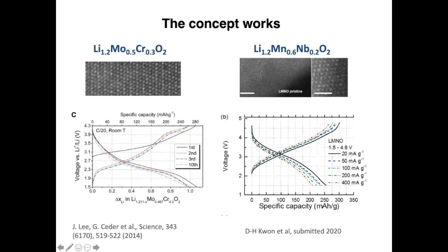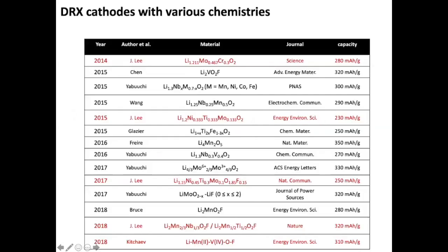Here's a material we made early on, a lithium molybdenum chromium oxide. Here's a STEM picture. It's fully disordered. It's really a rock salt, but you see you can cycle one lithium per formula unit, so 280 milliamp hours per gram. Here's another material. This related class has been studied a lot. 20% lithium excess, manganese niobium material, fully disordered. And I see, again, well over 200 milliamp hours per gram. So the model of diffusing through percolating zero TM pathways really works.